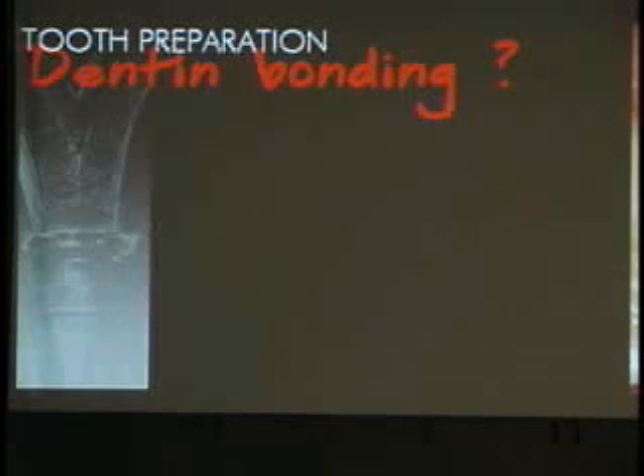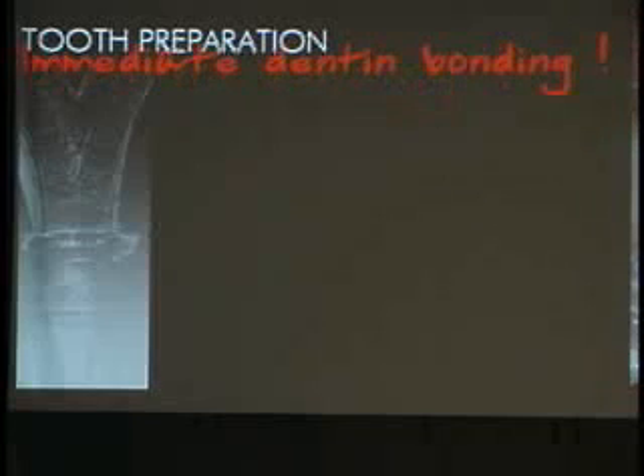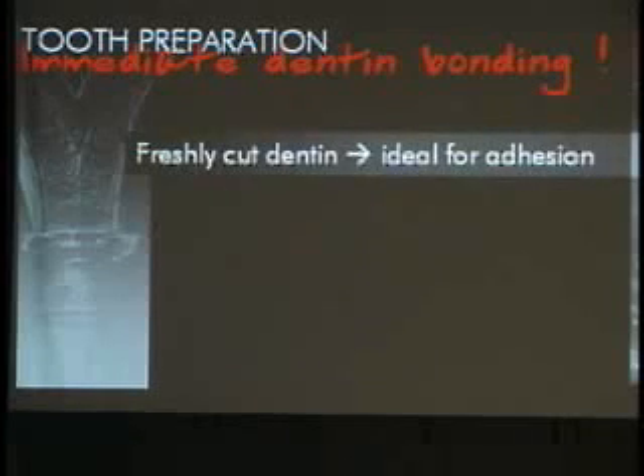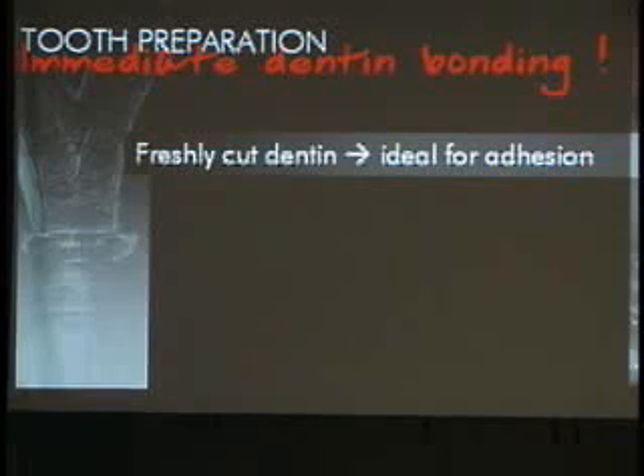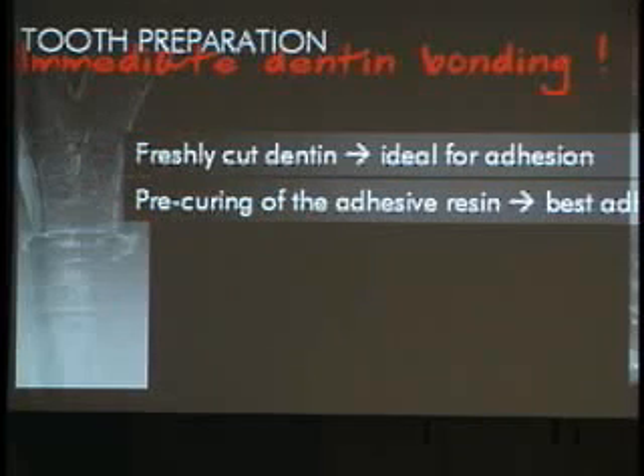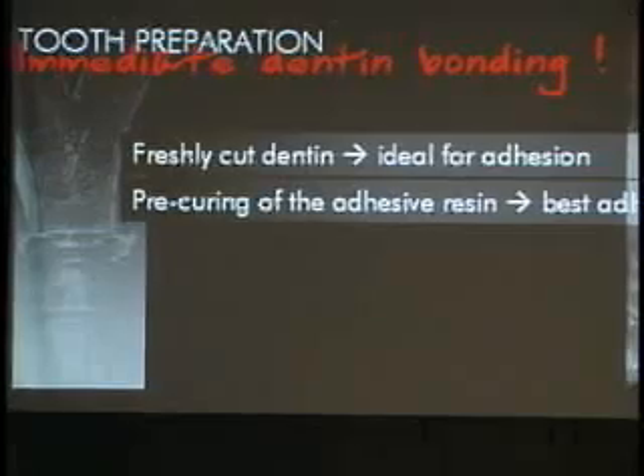The only thing that really I do different today, of course, is the dentin bonding, because we know that today we can bond to dentin very efficiently, which increases significantly the prognosis of these restorations. And we need to know that when we bond to dentin, using an indirect technique, we have to be careful, because dentin cannot be left exposed to the oral environment during the provisional stage. This is why we learned recently, and we are doing some research now on that, the dentin must be sealed straight away when the cavity is prepared, because dentin must be sealed when it's freshly cut, uncontaminated. It's best for adhesion. It will allow you to also cure the adhesive resin, which you can't do if you don't seal dentin at the time of preparation.